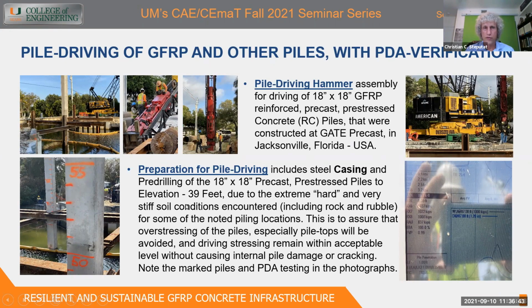So we needed to pre-drill to an elevation of -39 feet in order to start our driving, because as you all know, for deep foundations, we have a minimum amount of embedment that we need, as well as a certain load. In this case, it's a relatively minor bridge, only requiring 200 kips per pile. 200 kips is not very much, 200,000 pounds. So I looked at pile dynamic analysis while we installed them, especially since they are GFRP reinforced and pre-stressed. And we basically had to keep our driving stresses within the DOT limited range in order not to overstress the piles so we could use the piles.